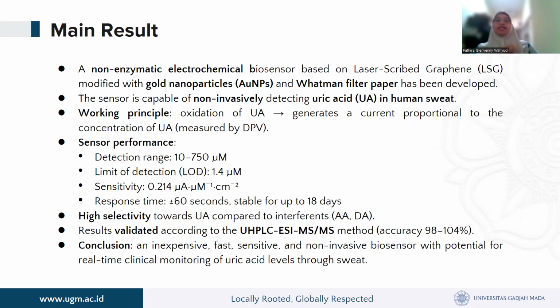Sensor performance: detection range is about 10 to 750 micromolar, limit of detection 1.4 micromolar, sensitivity 0.214, and response time about 60 seconds, stable for up to 18 days. High selectivity towards UA compared to interferents such as ascorbic acid or dopamine. Results validated against the UHPLC-ESI-MS method, with accuracy 98 to 104%. The conclusion: an inexpensive, fast, sensitive, and non-invasive paper-based sensor with potential for real-time clinical monitoring of uric acid levels through sweat.